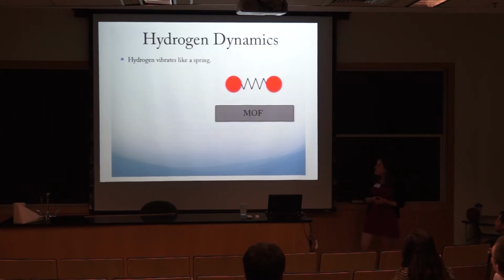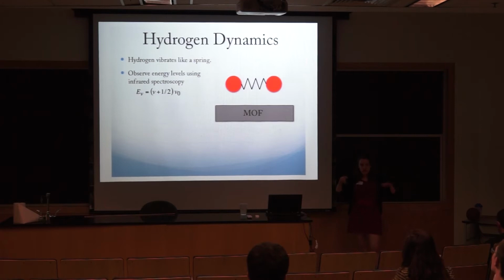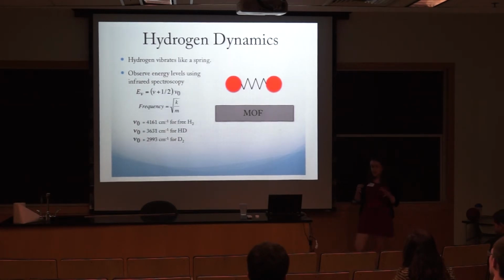So hydrogen, it's like a spring. You can model it as a simple harmonic oscillator, so it has some vibration. And we observe this vibration as energy levels in our infrared spectrum. So you see different peaks at different frequencies, and that tells you the vibrational levels of the hydrogen. We can figure out what the composition of a gas is that's in the MOF by looking at different frequencies. So the frequency goes as root K over M, so K being the spring constant and M being the mass.